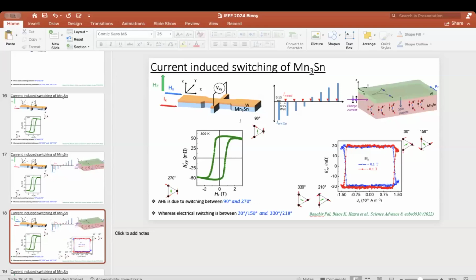Okay, yeah, it answered. Does the thickness of the manganese play a role? See, in this thickness range, we don't see any role. We measured different thicknesses, which I didn't show here: 30 nanometer, 40 nanometer, 60, 80, 100. So from 30 to 100 nanometer, we always observe 40% switching. That is summarized in the supplementary data in this paper. So it doesn't matter. The switching magnitude is independent of thickness.